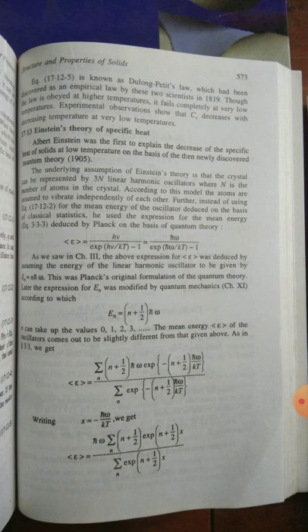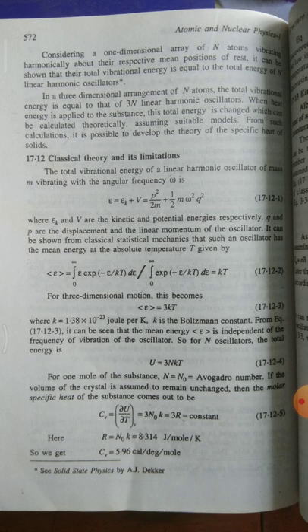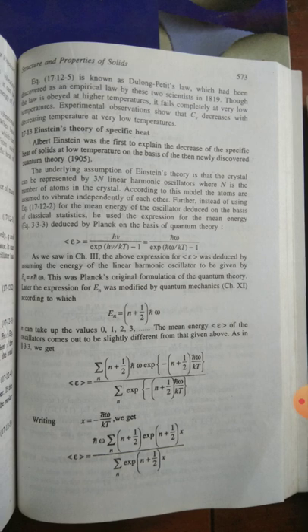Next topic, 17.12.5. Okay, this equation, Cv is equal to (dU/dT) at constant V is equal to 3 n naught k is equal to 3R is equal to constant, is known as Dulong-Petit's law, which had been discovered as an empirical law by these two scientists in 1819. Thus, the law is obeyed at higher temperature, but it fails completely at very low temperature. Experimental observations show that Cv decreases with decreasing temperature at very low temperature.